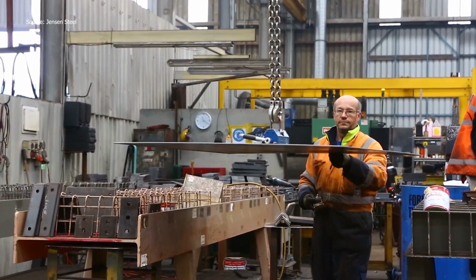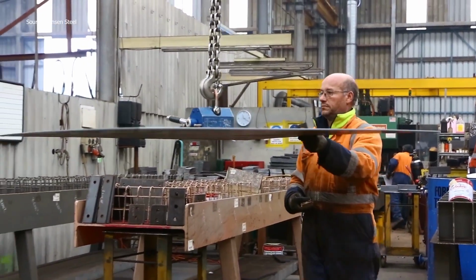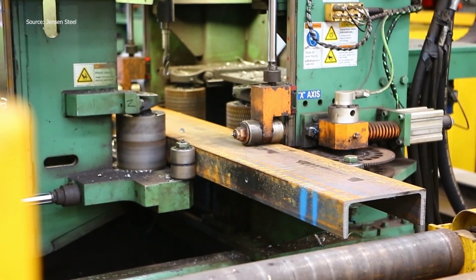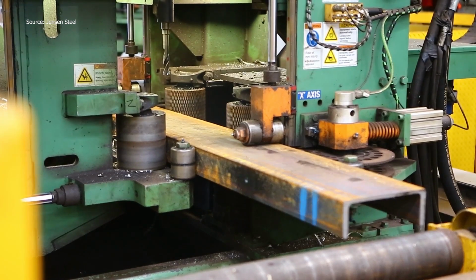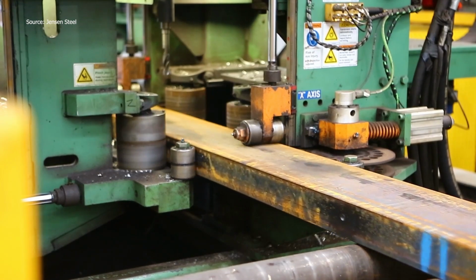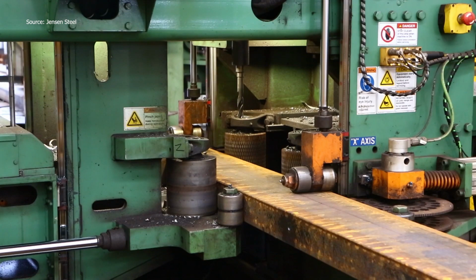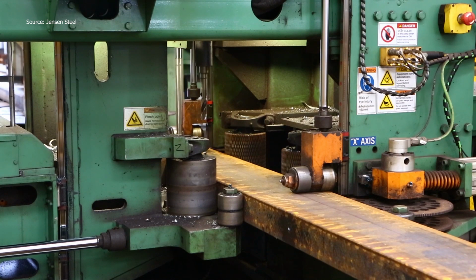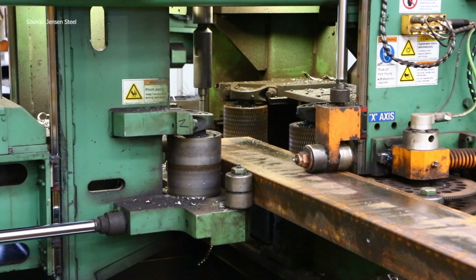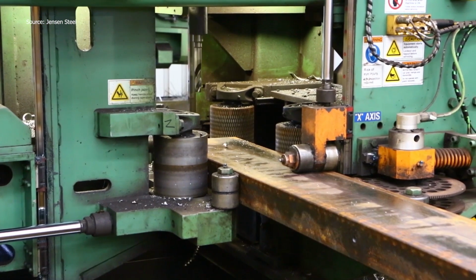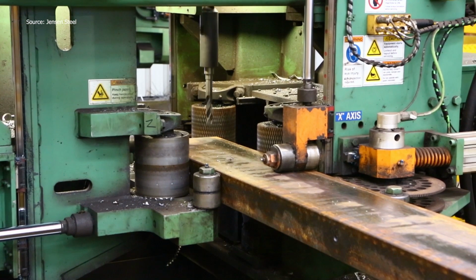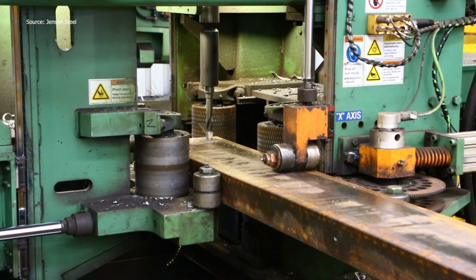Assemblers tack together the steel components to create the I-beam's core structure. Every fit-up is checked to maintain exact geometry. Welders then use multi-pass and submerged arc welding to achieve strong, deep joints, following strict welding procedures for marine-grade steel. Each weld is scrutinized with ultrasonic, magnetic, and visual inspections, guaranteeing that every seam meets exacting standards.